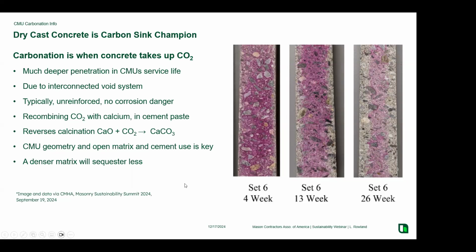CO2. So these are sections of block. In 4 weeks, you can see that we're getting into this a little bit into the surface as that block is exposed to the atmosphere for a couple more weeks. Where we're at 13 weeks, you can see it's penetrated even further, and then this is in a half a year. It's penetrated almost completely through that concrete matrix of that CMU. So the natural carbonation reverses the calcination process. So you've taken calcium with CO2 and recombined that to make new CaCO3. Essentially, you're making limestone in place here.